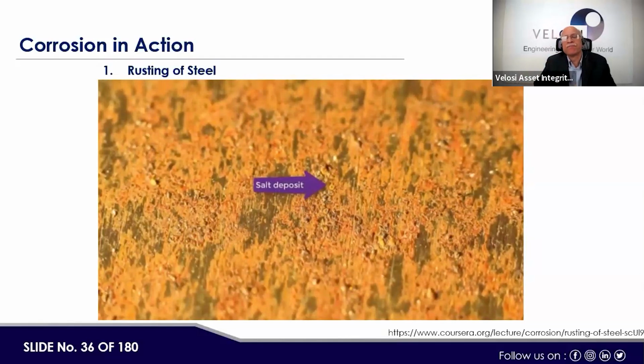The corroded parts of the steel are the anodes, where the anodic reaction, metal dissolution and rust formation, has occurred. Perhaps surprisingly, some areas of the steel have remained uncorroded during the 24 hours of exposure. These areas are the cathodes, where the cathodic reaction, oxygen reduction, has been occurring. Since no metal is corroded in these areas, the steel remains shiny. During the process of corrosion, anodes and cathodes move around until eventually, after a sufficiently long period of exposure, the whole of the surface will be covered in iron oxide corrosion product. This is a good example of how anodes and cathodes are as distinctive as the opposite ends of a battery and must occur at different locations on a corroding metal. Let's look at the movie again.